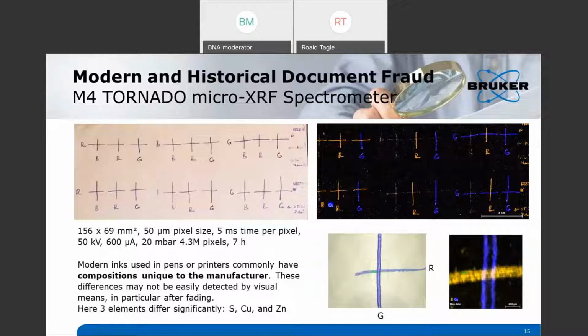So what you see here is the scan of the sheet of paper and a display of how sulfur and copper are distributed on the sample, marker elements for the different inks. So of course, with micro-XRF, you get elemental information on your inks. Additionally, on the top right image, the stronger sulfur signal is characterized by the stronger yellow color, and the copper by the strong blue color. So we also have some additional information.